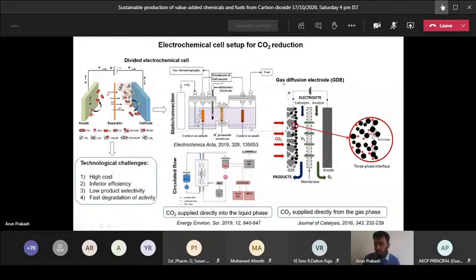So if you have aqueous electrolytes, mostly they are prepared using alkali metal cations like sodium and potassium. The best examples are sodium bicarbonate, potassium carbonate, potassium chloride, and potassium hydroxide. So the best electrolyte used so far is potassium bicarbonate. Most of the people who are working on CO2 reduction use potassium bicarbonate. Non-aqueous electrolytes can be used to increase the CO2 solubility, because CO2 will not dissolve easily in aqueous electrolyte.